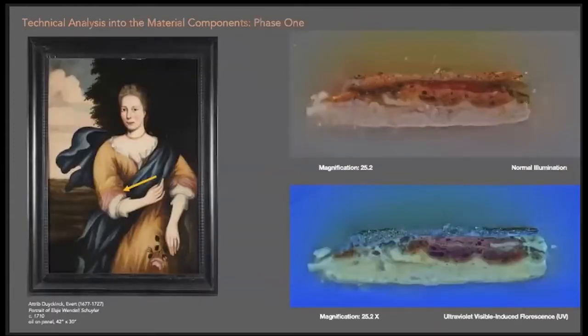In the portrait of Elsje Wendell Schuyler, painted by the Dutch limner Evert Duyckinck, the layer containing red lake does not have much lead white mixed in and appears as a more homogeneous, almost jelly-like application of a rich magenta glaze used to paint her pink cuffs, rose, and lips. And for those who are looking at the two images of the cross sections on the right, we're looking at that deep magenta, almost jelly-like second layer from the top that also fluoresces a slight pink in the UV or ultraviolet image.